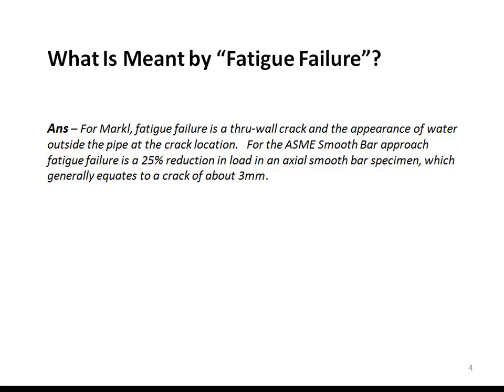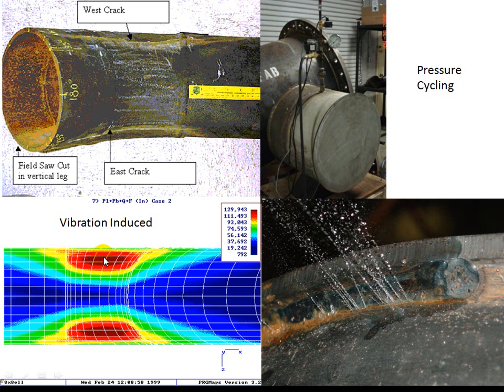So let's take a look at the appearance of different types of through-wall fatigue cracks. On the left is a cracked elbow. The finite element model on the bottom shows high stresses at the crack location. This cracking was due to repeated large displacement caused by dynamic loading in a relatively unsupported pipe.